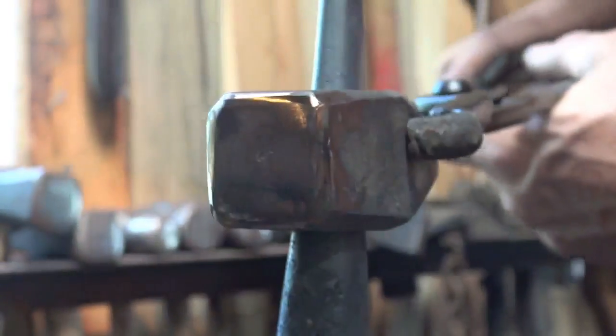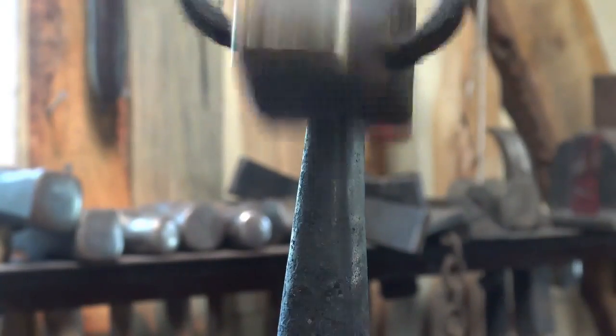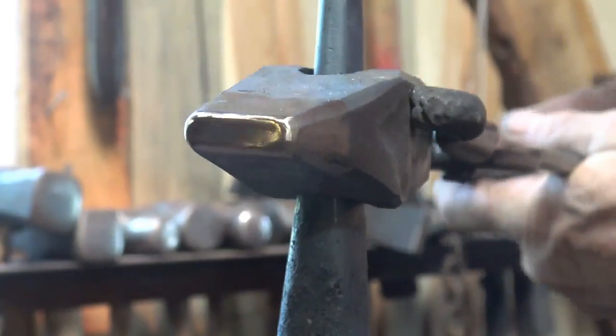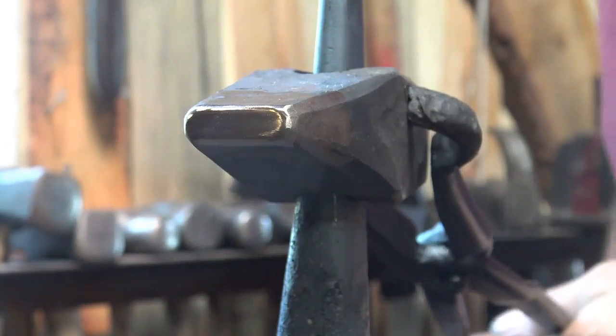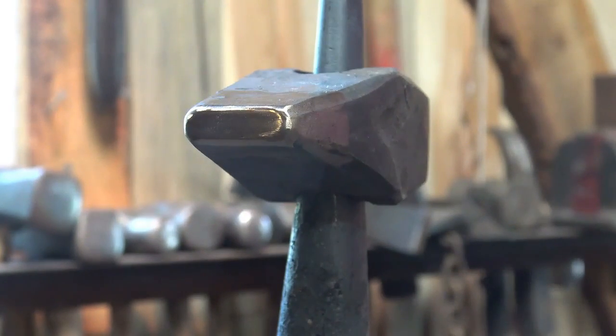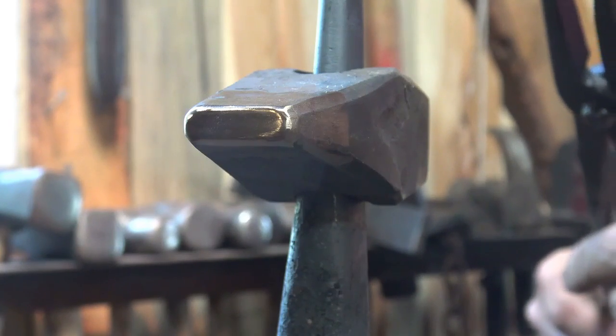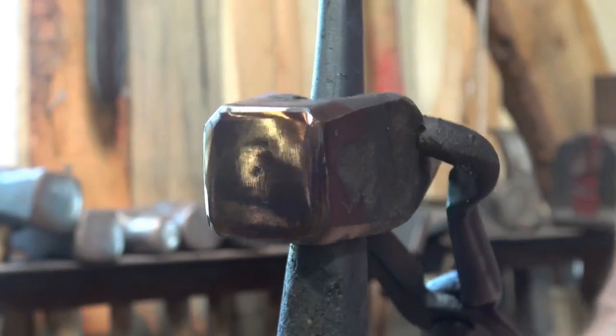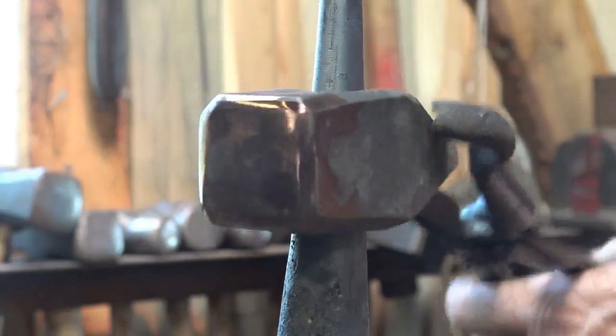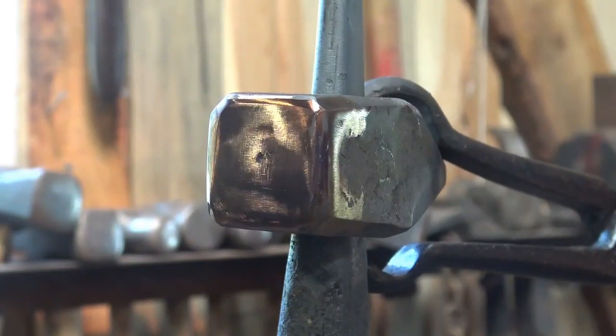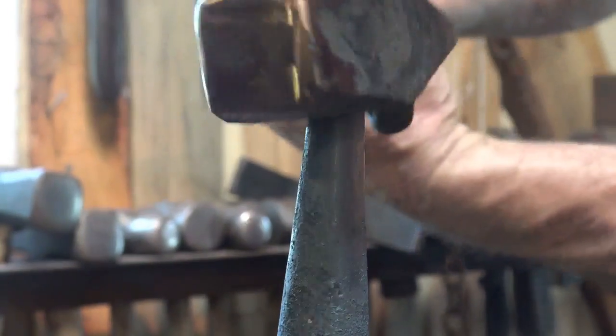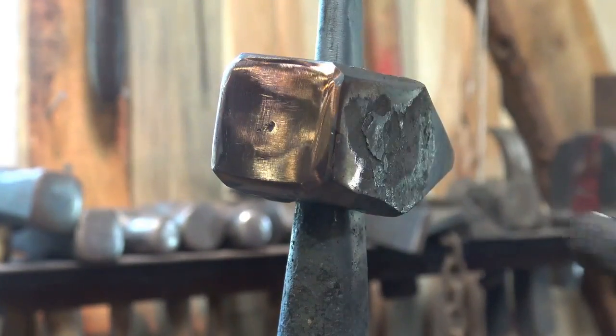The peen is heating up at about the same rate. The pin is cooling down quite a bit, so it's not heating up fast. This is a very nice controlled way to do this. I've actually had to reheat the pin one time. Just set the hammer aside, it stays pretty hot. Bring the pin back up to a bright red heat and put it back on there. Getting the slightest hint of purple, so that purple to bronze range is what we refer to as peacock. And that's probably about 550.